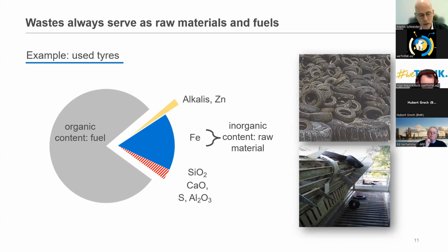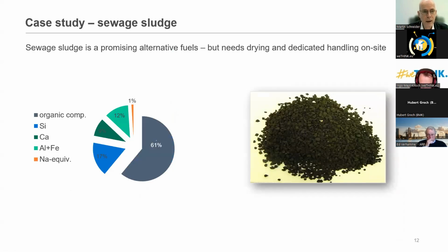We have to make sure that these materials are pre-treated or controlled with respect to their trace element concentration, for example, to the degree as we have heard from Austria. Now, a case study here for sewage sludge is very interesting. It's roughly two thirds organic components, biomass, and the rest again is silica that we are in need of, and calcium that we are in need of. And we have aluminum and iron that we are in need of in order to form the clinker phase.